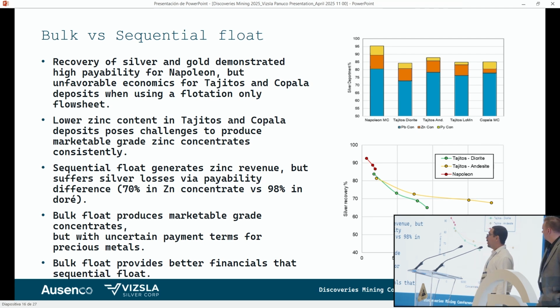The payability of the silver in the zinc concentrate is around 70% compared to 98% in doré. So doing a sequential float circuit actually resulted in losses, in spite of having the sellable zinc concentrate. And also in the later years, it was going to be pretty hard to get a sellable zinc concentrate on the Tajitos and the Copala deposits.